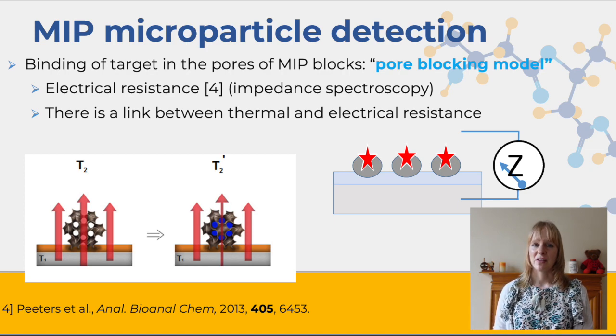And this concept was later patented and was used with a lot of these molecularly imprinted polymers, ranging from cancer cells to proteins, but also for small molecules. So you can imagine there's a wide variety in these microparticles. They all have different sizes, and that also means that there's a distribution of the binding affinity. Another big problem is, if you're extracting your target afterwards, and it's embedded within a big clunky particle, it takes a long time and it can lead to a problem with diffusion for binding and extraction. Now, what people tend to do nowadays is move towards either films or nanoparticles.